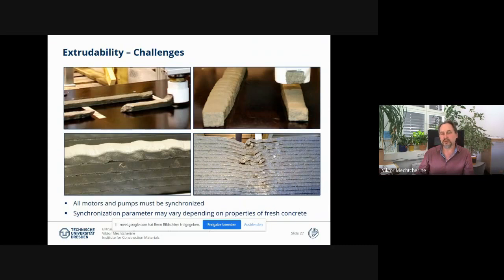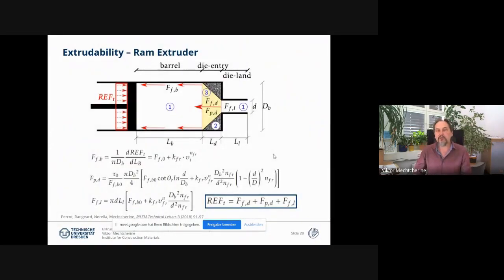So what we need here is, of course, a very good control of the material flow, and we can achieve this by synchronizing all involved motors moving the print head, but also the motors of the pump delivering the material. But what is the trick, I think, is that these synchronization parameters may vary considerably depending on the properties of the fresh concrete, which may also change during the printing process due to aging of concrete in the first hours. We can have some changes in these properties, and then we need to adapt, of course, the steering of the machine accordingly.